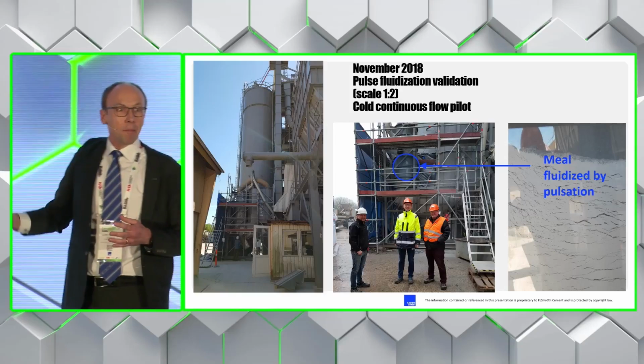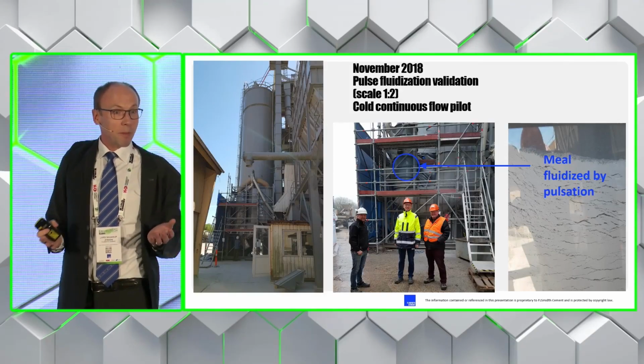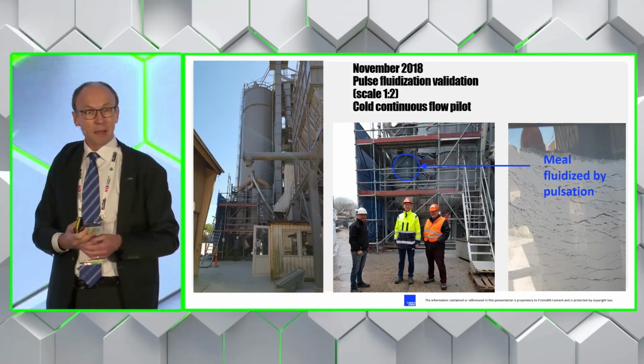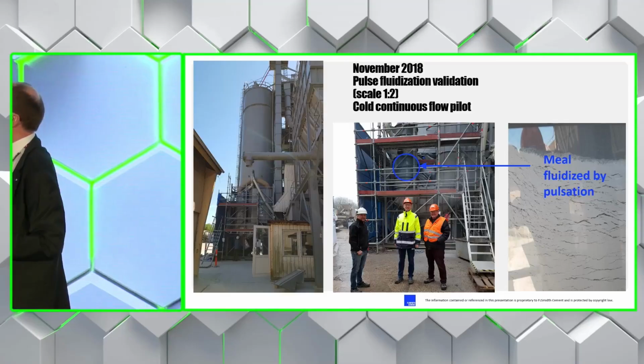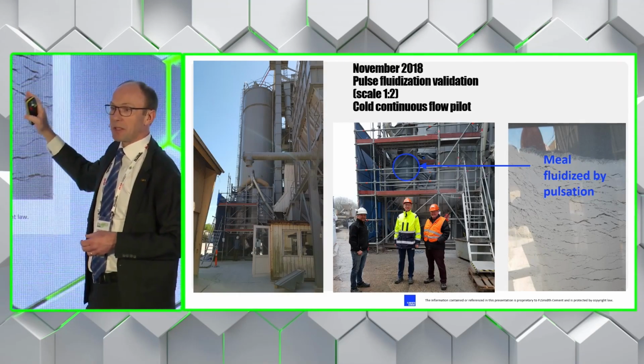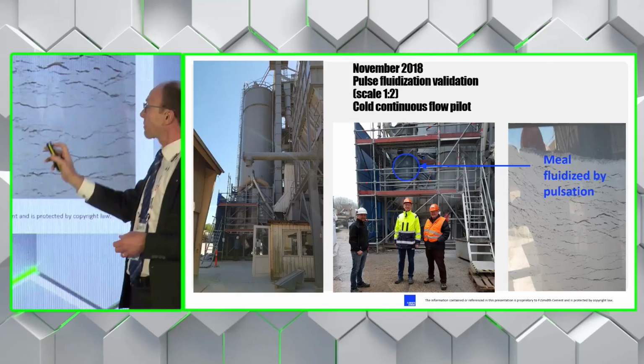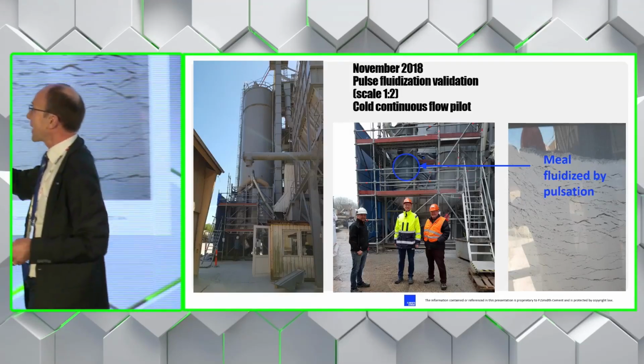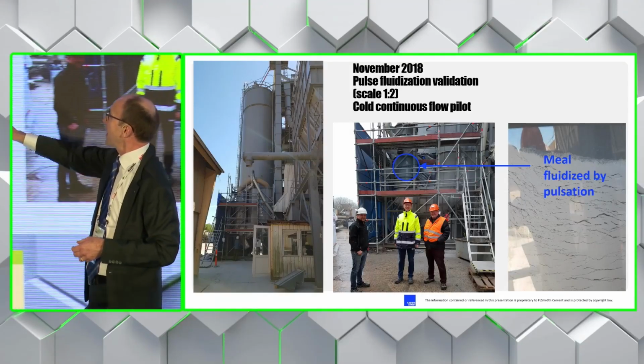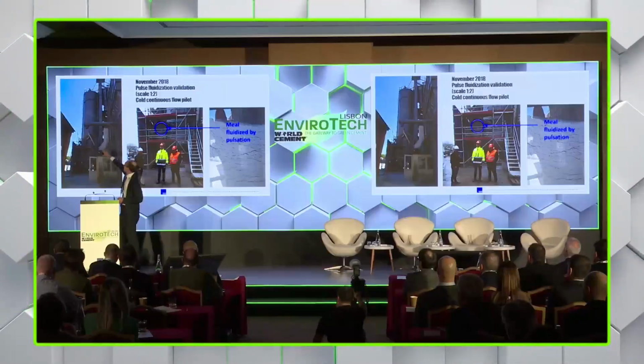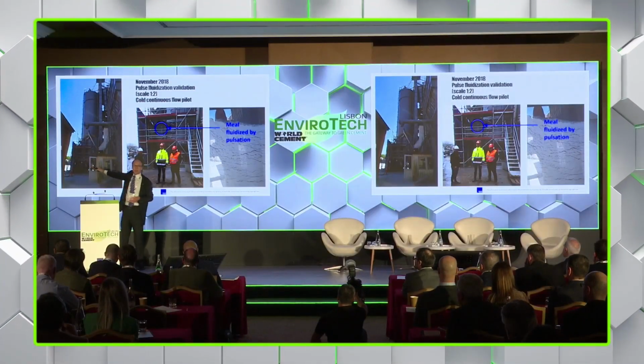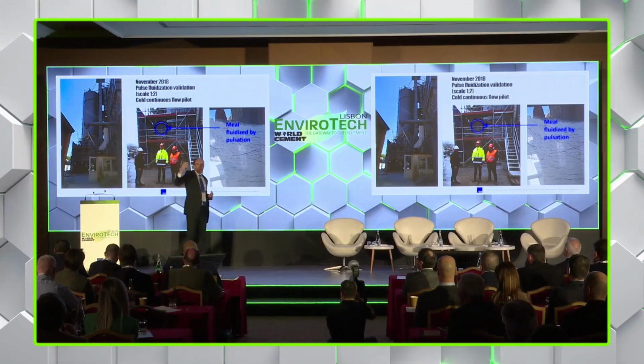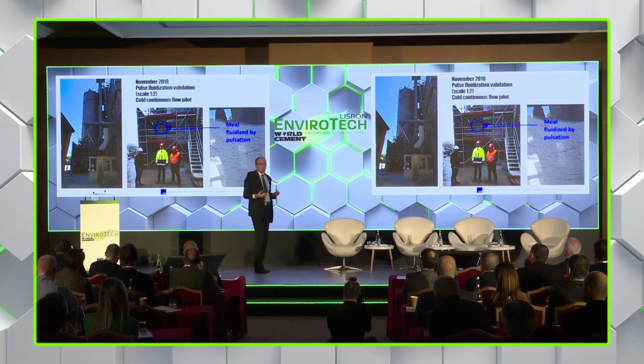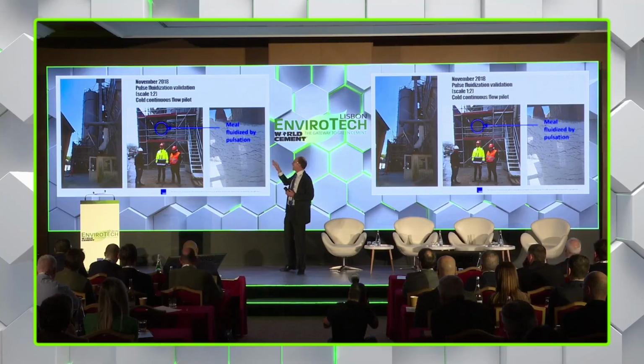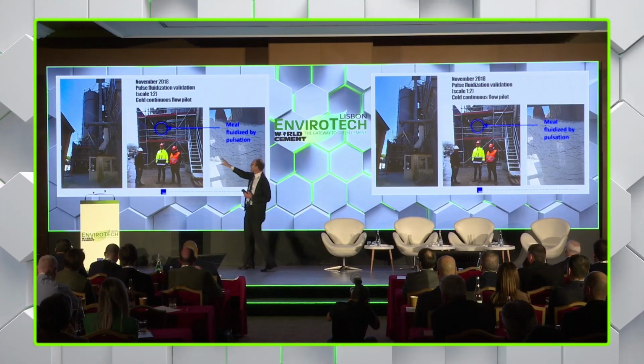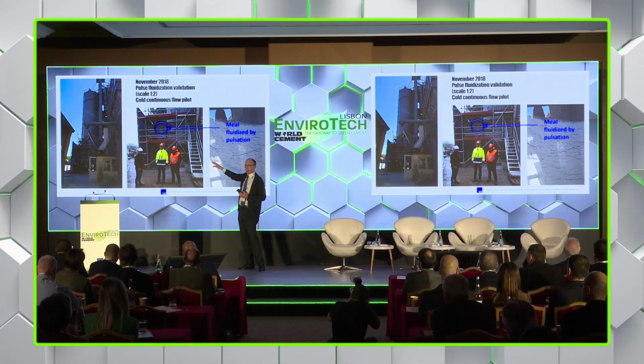Now we had to scale up by about 2,000 times from our hot pilot installation, and to do that with this new pulsed aeration technique, we built a pilot scale installation. You can see it over here in front of the big silo. This is the scale 1 to 2 pilot installation which we built. We then recirculated the meal over the silo and then used this to scale up and get the design details right for this pulsed aeration.